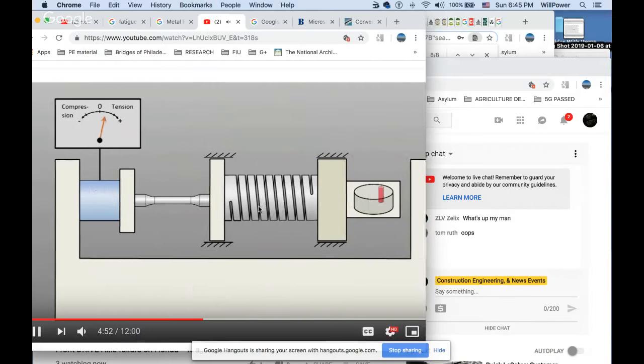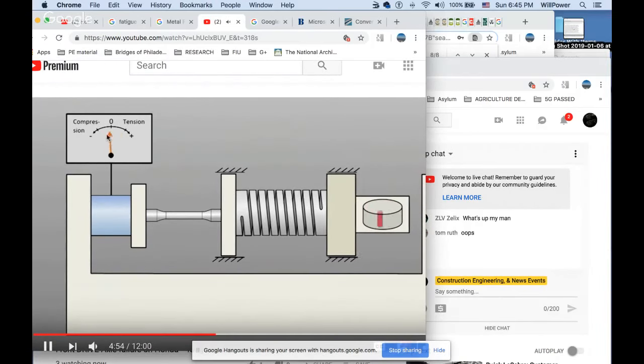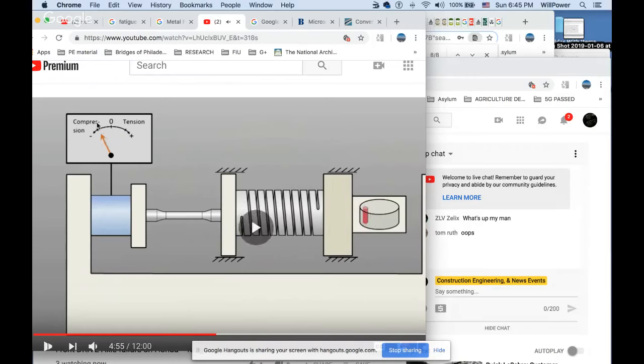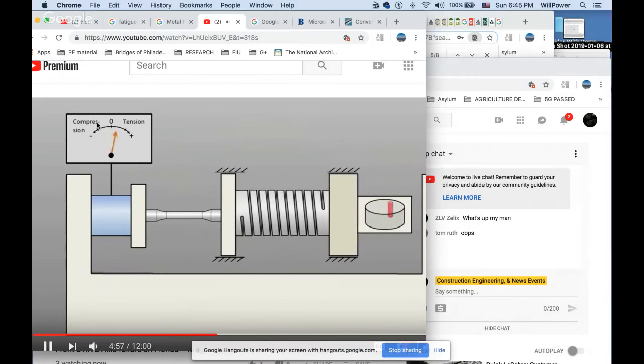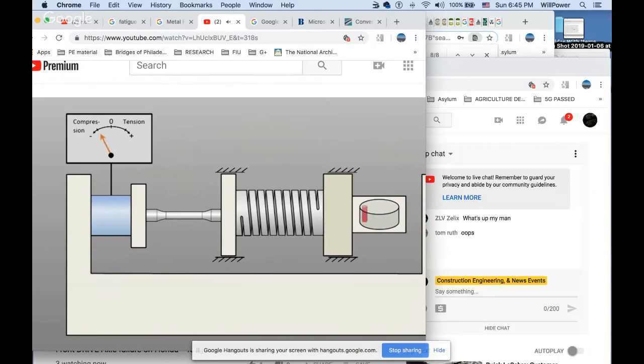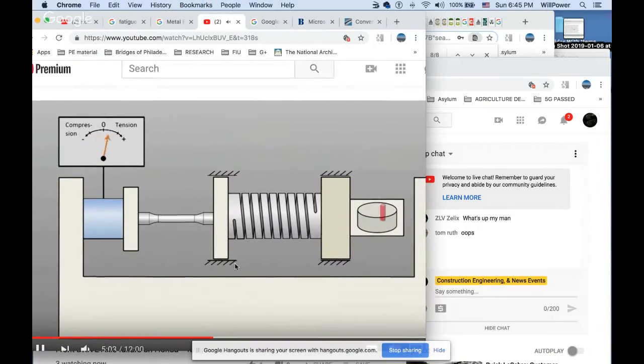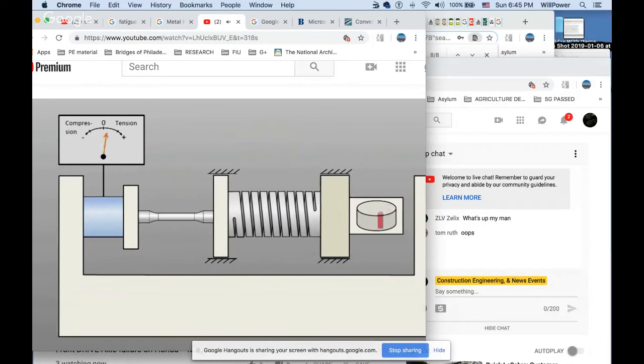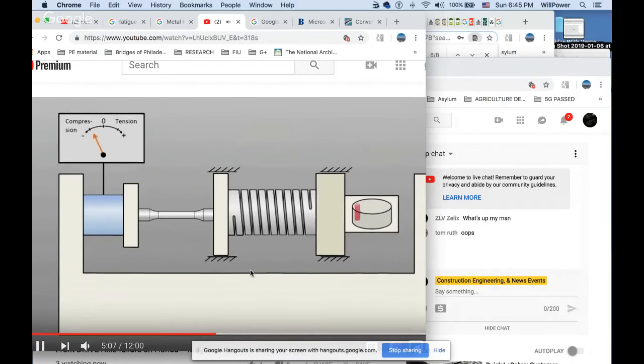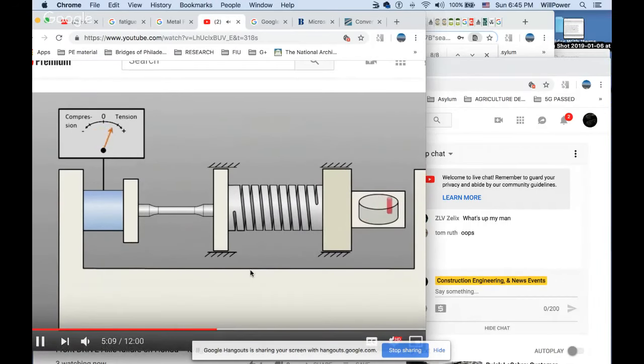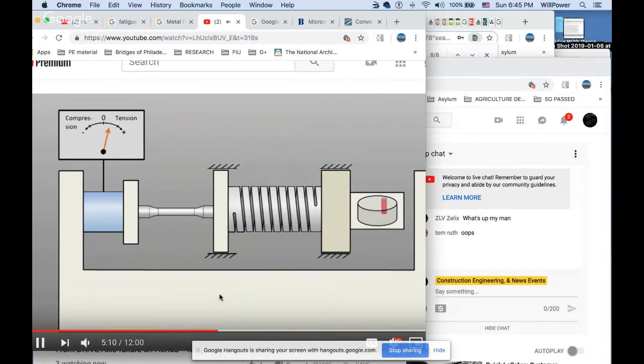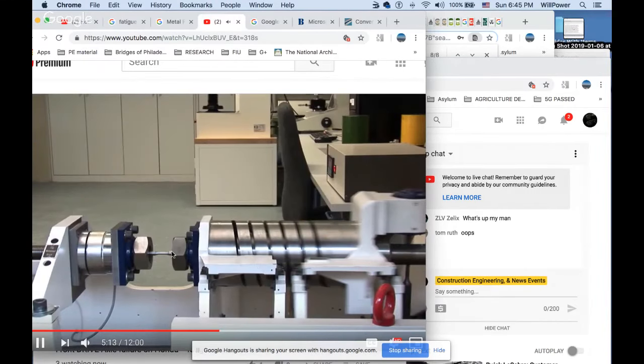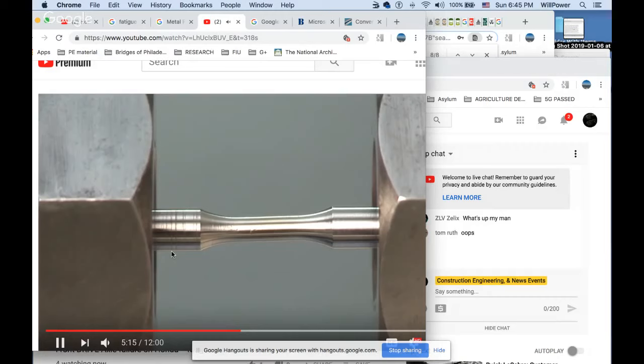Via the spring, the test force acts on the specimen. So it goes to 0. By varying the excitation frequency of the imbalance, the test force can be controlled. In our case, the specimen is loaded with about 25 cycles per second. Now let's go. Meanwhile, the first specimen has already endured over 300,000 load cycles.